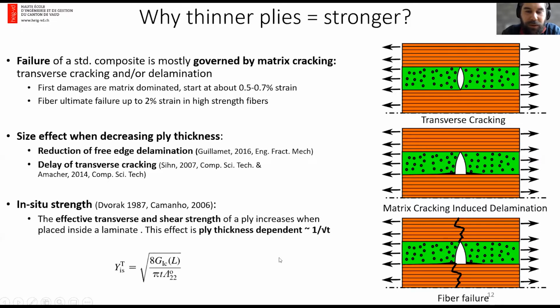And due to this, we can see that based on fracture mechanics concepts, we could derive that the effective strength of a ply in situ in transverse loading is a function of the toughness of the composite in the longitudinal intralaminar cracking and the ply thickness that appears here. So we can see here that the strength of a transverse ply scales theoretically with 1/square root of the ply thickness. And this has been demonstrated in many papers, and we also observed it.